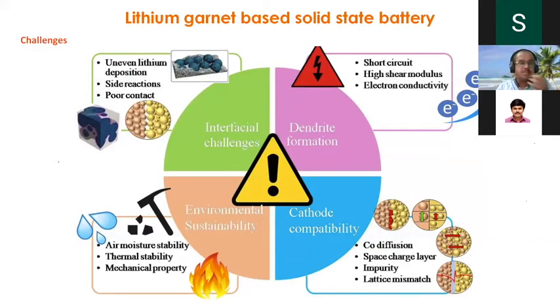That's the time the whole world picked this up. Then people started to understand the challenges in solid state batteries, particularly lithium garnet based batteries. Because liquid-solid interfaces are fabricated in the conventional liquid battery. But when you have a solid, physics knows very well that solid interfaces are really tough to crack. The biggest problem is the interfacial challenges. On the anode side, there were uneven lithium depositions, side reactions with the cathodes, and poor solid-solid contact. When I want to use lithium, dendrite is the biggest issue.